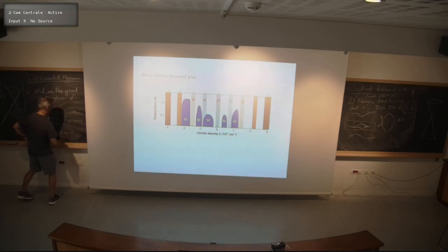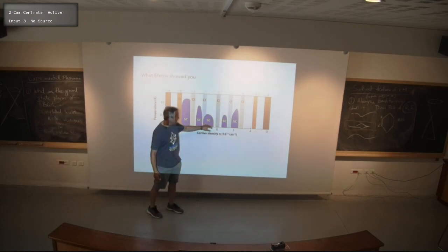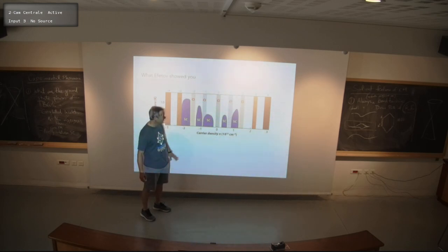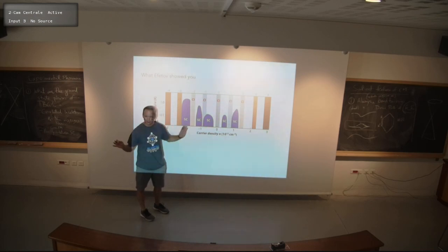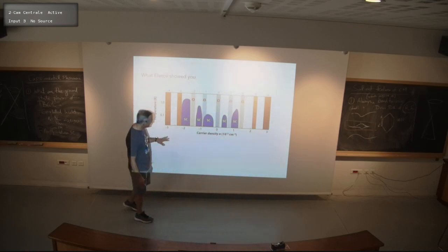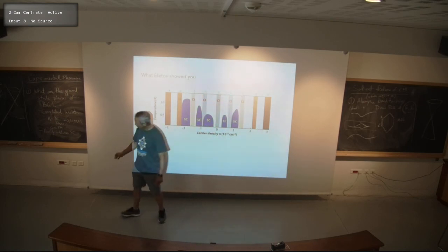One sees superconductivity. And these are Dimitri's results, more or less drawn in cartoon form here. You can see for the most part the superconductivity he finds is between these correlated insulators, although even this is not studying a lot of samples. I don't know how many, maybe 2 samples are used to put together this diagram, more or less. And even here you can see sometimes there's superconductivity overlapping where this correlated insulator is. Sometimes it just obliterates it.